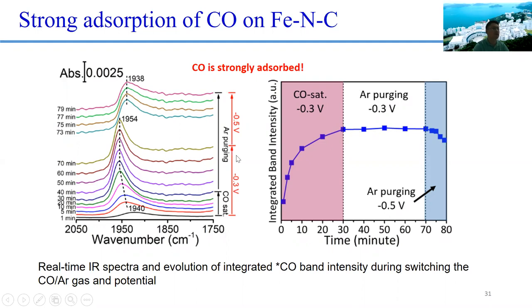And then we purged argon and jumped the voltage from minus 0.3 volt to minus 0.5 volt, which means reduction should happen. So the CO should be reduced and then removed from the surface. But we didn't see this. You can see the intensity of the CO is still very high. So that means the CO is actually not easy to remove in this case.